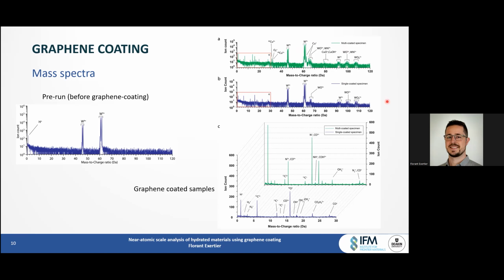The key points highlighted by these mass spectra are, first, the detection of carbon atoms from the graphene, which were also shown in the previous slide. So it peaks at 12. We've got C, we've got CO at 28. Then the second point is the presence of tungsten in the 2+ charge state, as can be seen here in both samples, which indicates a lower electrostatic field. And finally, we have the presence of copper, which is essentially contamination from the graphene coating protocol, but in this case was used as a proxy to estimate the electrostatic field variations.